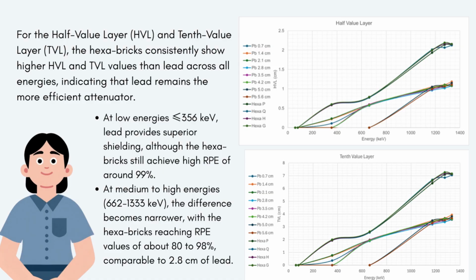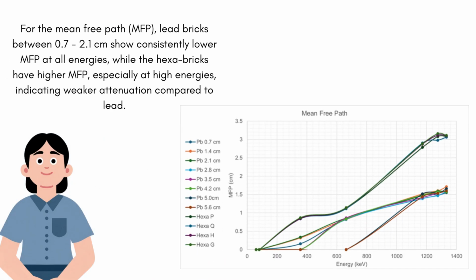At low energies, lead performs better, yet hexabricks achieve 99% RPE. At medium to high energies, they reach 80–98% RPE, close to 2.8 cm of lead. For the mean-free path, lead bricks between 0.7–2.1 cm show consistently lower values at all energies, while the hexabricks have higher values, especially at high energies, indicating weaker attenuation compared to lead.